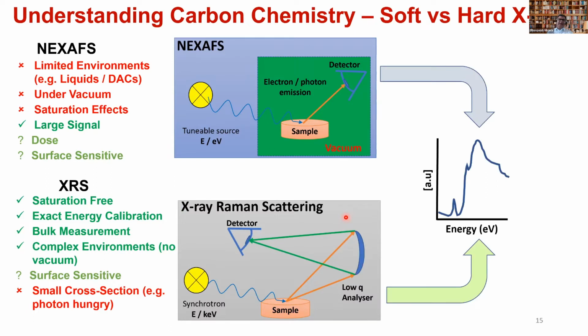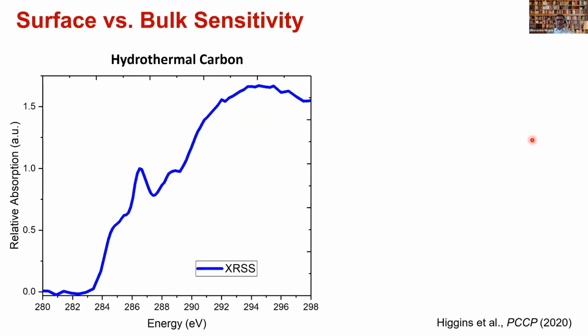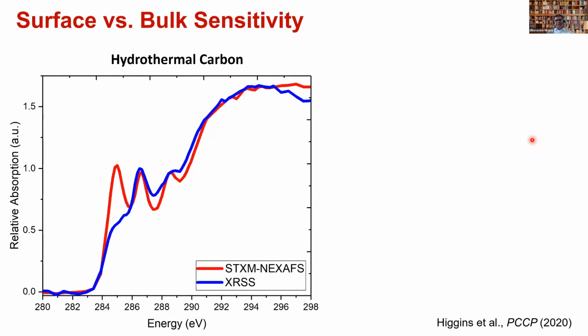So ideally, one can imagine that for many systems, one should get the same kind of spectrum, whether using NEXAFS or XRS. Any user who has actually used these would immediately say, no, that's not going to be the case, and rightly so, because there are differences between the two, and you'll see that right away. So here is hydrothermal carbon measured using XRS, and the exact same sample measured using NEXAFS. You see that there's a huge difference in the peak here, which we're still trying to make sense of.